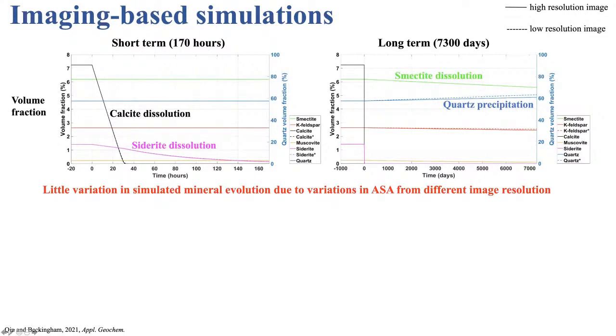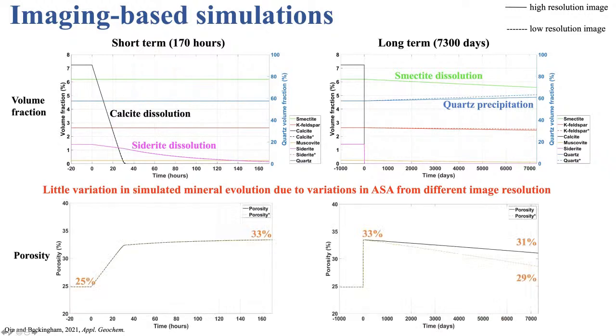If we look at longer time scales, now we start seeing smectite dissolution as well as quartz precipitation, and really little variation between the simulation results. In terms of how porosity is impacted, we see an initial increase in porosity from 25 to 33%. And then over long time scales, porosity starts reducing again to 29 to 31%. So there's some slight variations in the two results, but not very extreme.